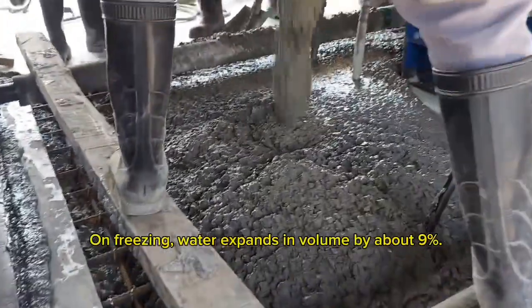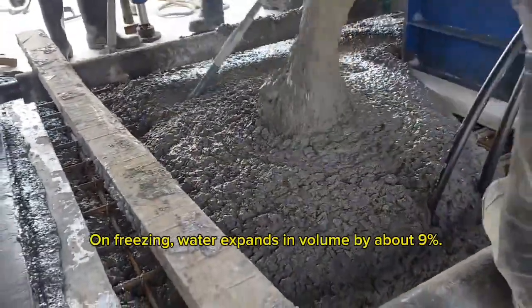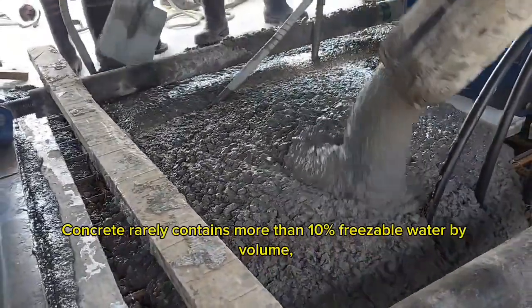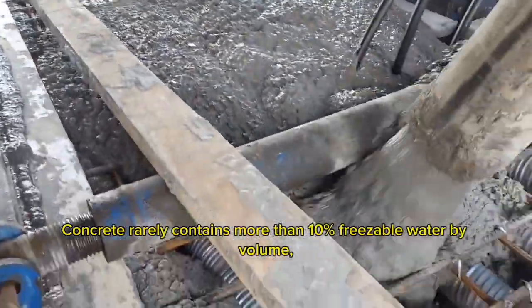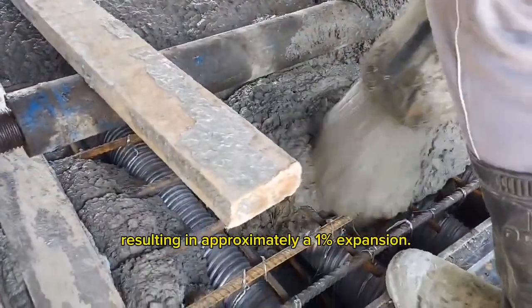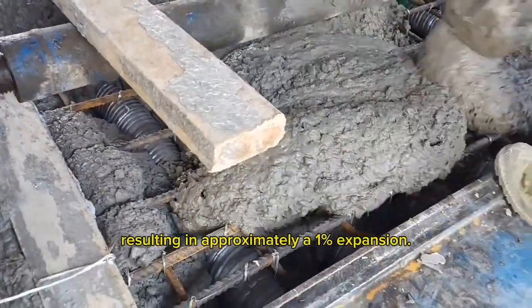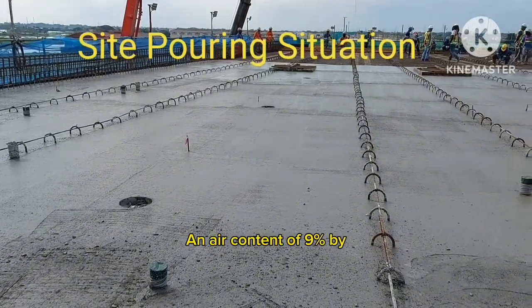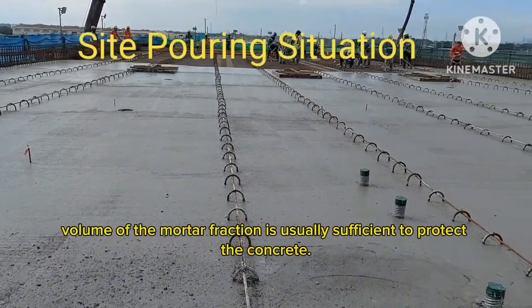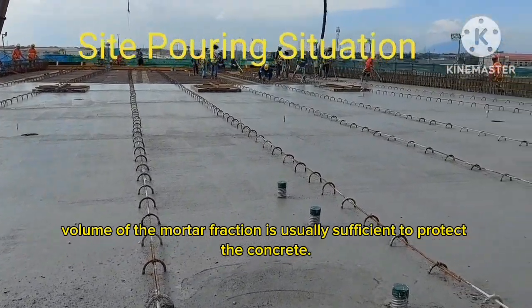On freezing, water expands in volume by about 9%. Concrete rarely contains more than 10% freezable water by volume, resulting in approximately a 1% expansion. An air content of 9% by volume of the mortar fraction is usually sufficient to protect the concrete.